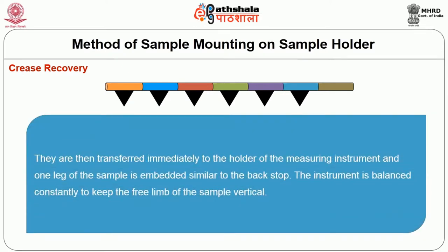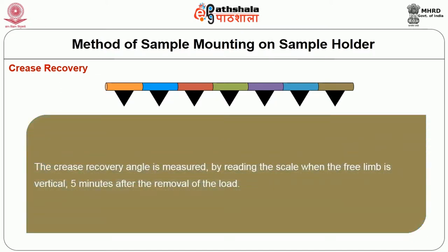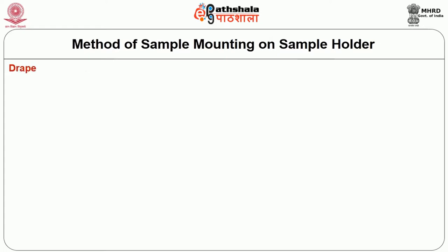They are then transferred immediately to the holder of the measuring instrument for crease recovery, and one leg of the sample is embedded in the backstop. The instrument is balanced constantly to keep the free limb of the sample vertical. The recovery angle is measured by reading the scale when the free limb is vertical, 5 minutes after the removal of the load. The last one in the serviceability of the woven fabric is drape.